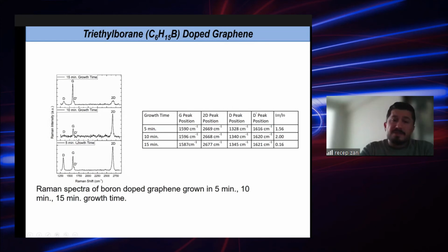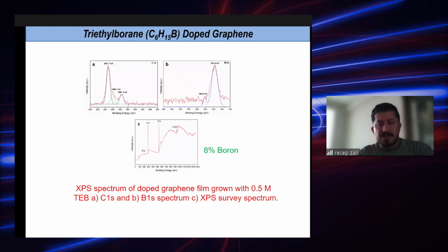I didn't show you before, but let me emphasize here, the D peak is related to defects. Yes, we know impurities can introduce defects, but more importantly, a shoulder of the G peak, which we call D prime, is associated with foreign atoms in the structure. So we see that in the Raman spectra, but to make sure these foreign atoms were boron, we proceeded further with XPS, X-ray photoelectron spectroscopy, to see the boron peaks, whether it is substitutional or just an addition or on the edge, or which type.